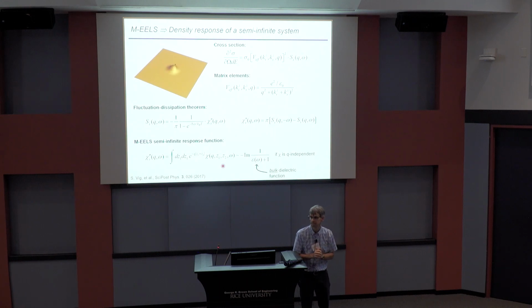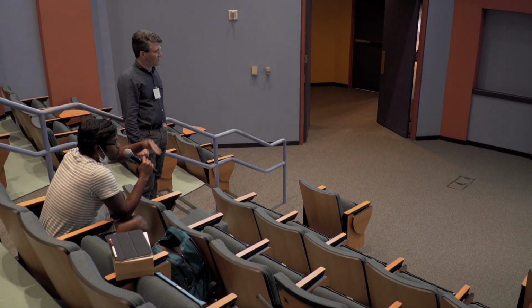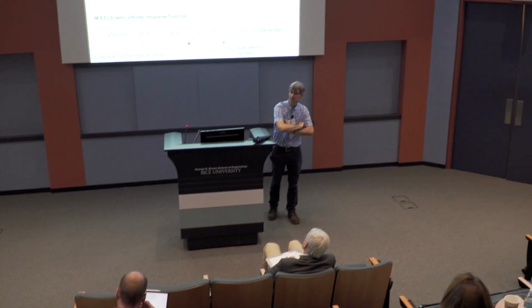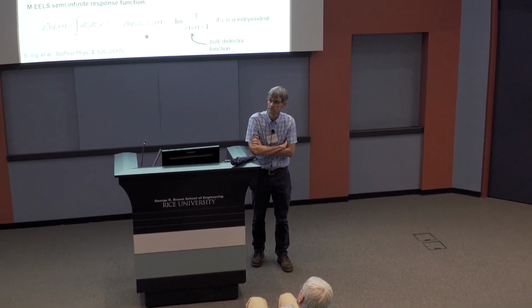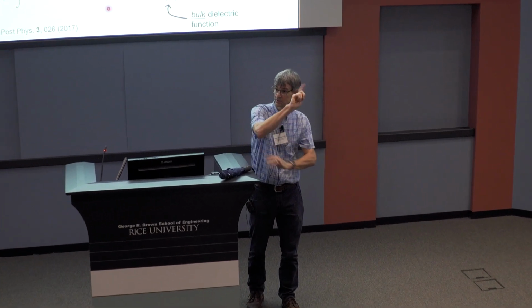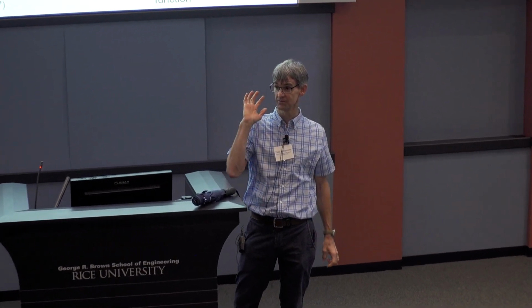So for bismuth selenide, did you still get this minimum at finite q, and were you able to get an estimate for this? No, because the dynamics in bismuth selenide aren't relaxational. A gamma only means something if it's a relaxational system, meaning there's no energy scale, there's no peak, right, in the cuprates at finite Q. In bismuth selenide, there always is a peak there, so there's no gamma to discuss.